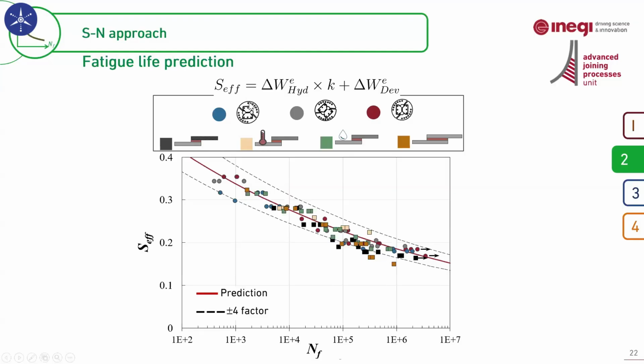I would say that this is one of the most universal fatigue models developed so far for fatigue life analysis of adhesive joints. This model can provide a good prediction of fatigue life for different joint geometries, at different loading angles, different materials, single lap joints with different overlap sizes, with different substrate materials, and even at different environmental conditions, humidity, and temperature. And here you see the red line shows the prediction based on this model, and the symbols and dots are the experimental data.